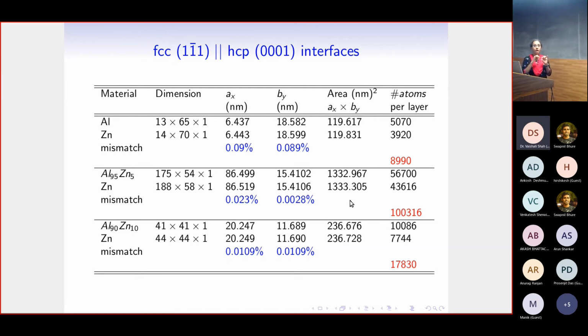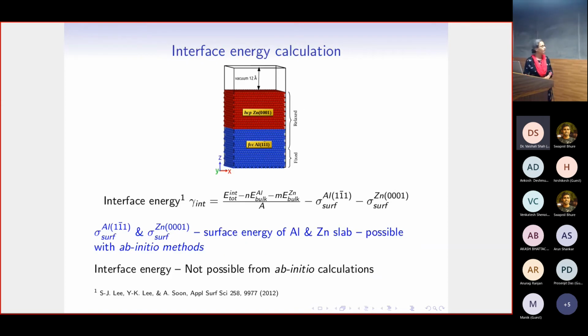And this is only for one single layer that we are considering in a particular orientation of that surface. Okay. And for 9010, it comes out to be close to 20,000. So this was a problem now. We cannot really solve it by first principles methods, because this amount of atoms cannot be handled even with the best computing infrastructure we have anywhere in the world. We cannot do this by first principles.